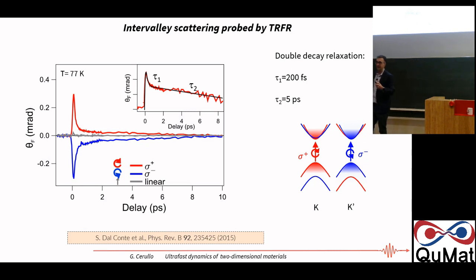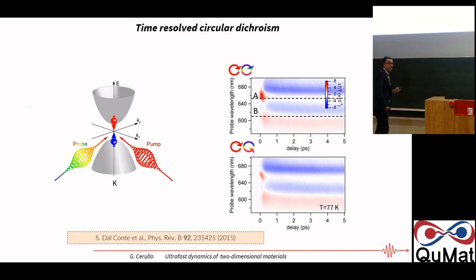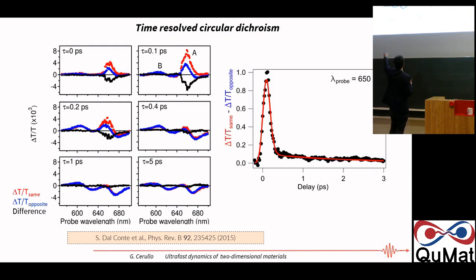So we can confirm this result with a different measurement, which is time-resolved circular dichroism. So what do we do? We do a pump-probe. In this case, both pump and probe are circularly polarized, but now we have the same helicity or the opposite helicity. In one case, we pump one valley and we probe the same valley. In the other case, we pump one valley and we probe the opposite valley. So if we look now at the dynamics, you see that same and opposite at time zero are clearly different. And you see there is a clear difference which is expected because of this essentially valley selectivity. But then as time passes, after 1 picosecond, the difference is very small, and after 5 picoseconds, the difference has disappeared. So there is a loss of this valley memory again within a few picoseconds.